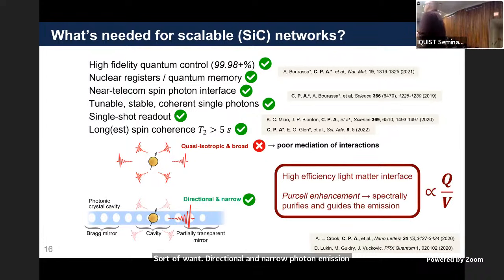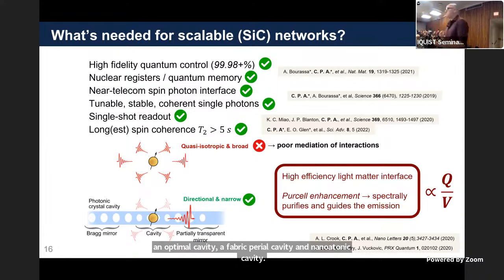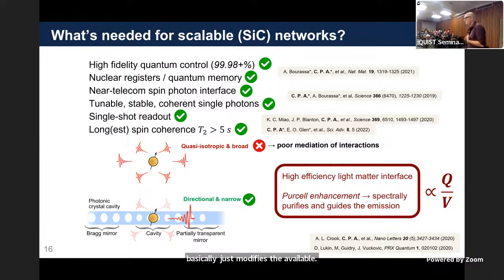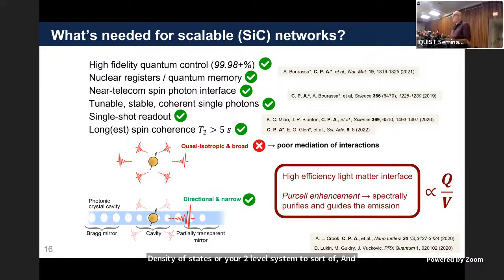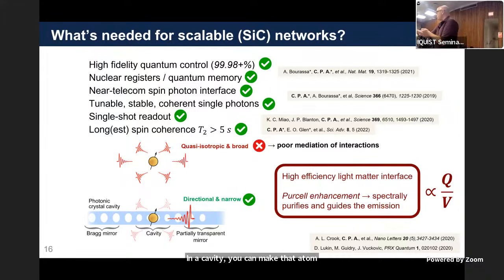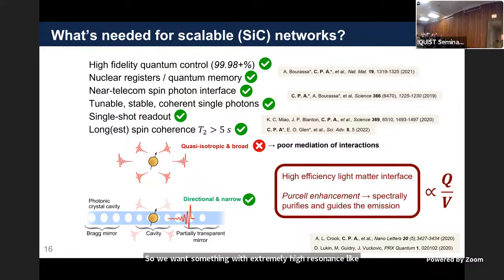And this is exactly where photonics comes into play. As some of you may know, if you put a two-level system in an optical cavity, a Fabry-Perot cavity, a nanophotonic cavity, there's this Purcell effect. That Purcell effect modifies the available density of states for your two-level system to emit its energy into. If you put your atom or your artificial atom in a cavity, you can make that atom preferentially emit in the cavity mode, which has a very specified spatial orientation and shape, and also a very specific spectral shape. We can turn this quasi-isotropic and broad emission into something directional and narrow through this Purcell effect, the strength of which scales as the quality factor of our optical resonator over the mode volume. So we want something with extremely high resonance, like lots of bounces in the mirrors.